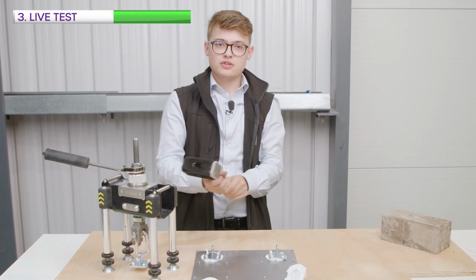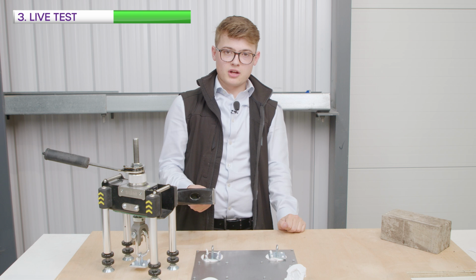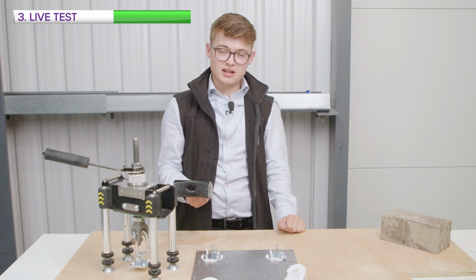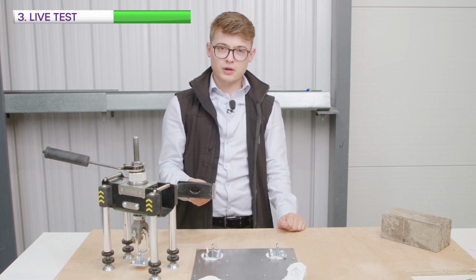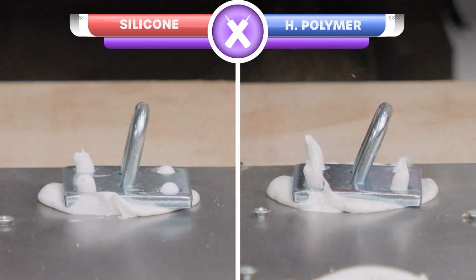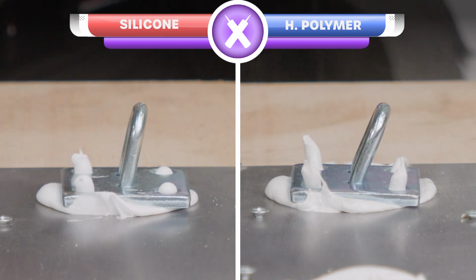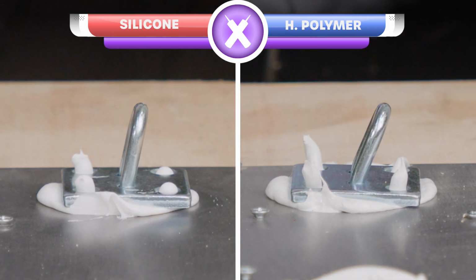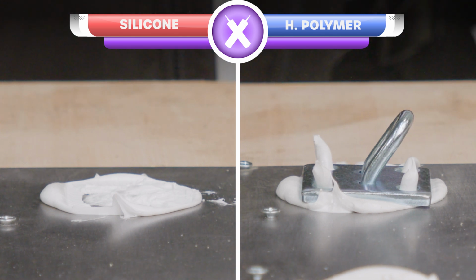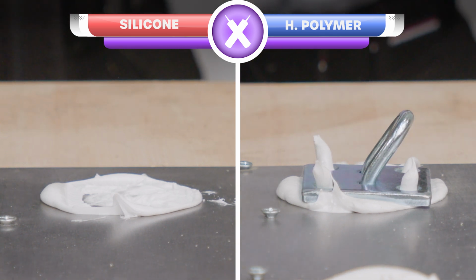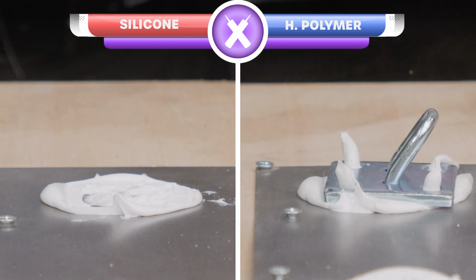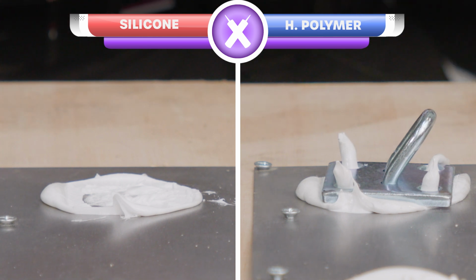The next test we're going to do is a flexibility test using this hammer. The test is conducted by hammering the pegs side on until one of them gives way. We can see that the peg bonded with silicone was displaced after one hit, while the hybrid polymer peg was able to withstand a few blows before resulting in the top of it being bent.